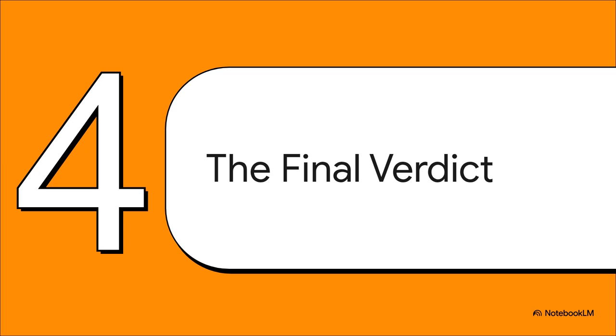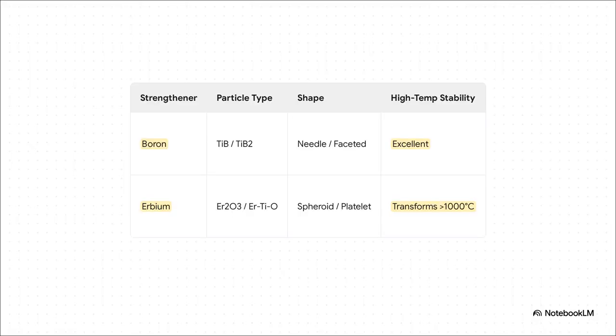So after digging through all the evidence on both boron and erbium, what was the final verdict from our 1991 scientific detectives? Okay, let's break it down side by side. You've got boron, which turned out to be really predictable. It formed its needles or blocks, and crucially, they stayed that way even when things got super hot. Erbium, though, was more of a shapeshifter. It formed spheres at lower temps, but then completely transformed into something else above 1,000 degrees Celsius.